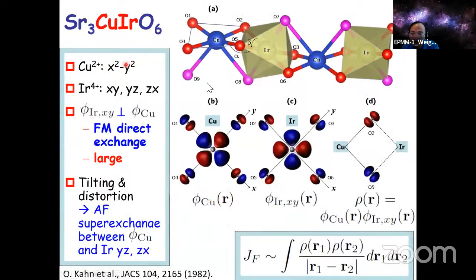So what's the mechanism? First is the relevant orbitals. The copper 2+ has the x squared minus y squared orbital as the active orbital. And for the iridium, you have xy, yz, and zx, the T2G 3 orbitals, and this is edge sharing. So that means you have a ferromagnetic direct exchange between the xy and the copper orbital, but you have antiferromagnetic superexchange between the copper x squared minus y squared and the iridium yz and zx orbitals. Okay.